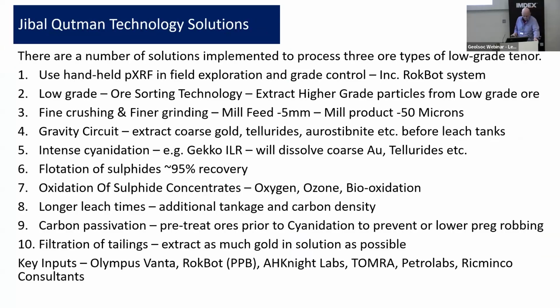The technology solutions we're going through at the moment, we make extensive use of handheld XRF in field exploration, and that will also be carried over into grade control. There's a number of elements, as I explained earlier, that also fingerprint, especially arsenic. This thing pops up with arsenic. We're looking at ore sorting because of the grade of the deposit. So fairly early on, Tomra will do a free test, like a 20-litre bucket of your selected samples, to see whether you can upgrade the grade from, say, 0.5, generally a doubling of grade, if you get the parameters right and the sizing right for ore sorting test work.